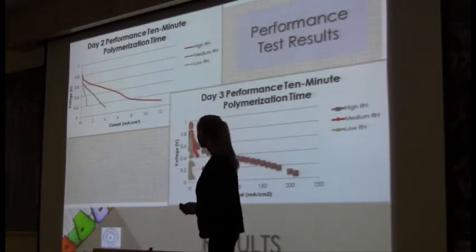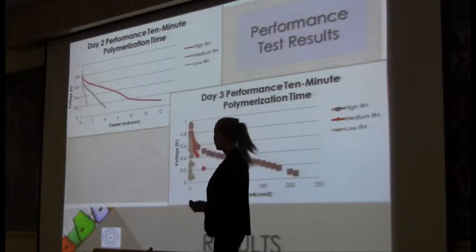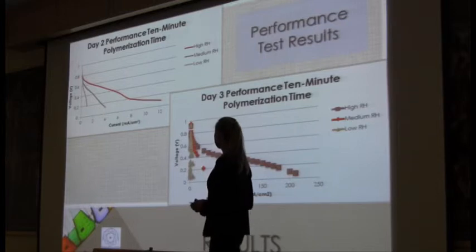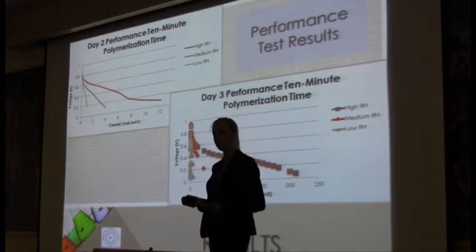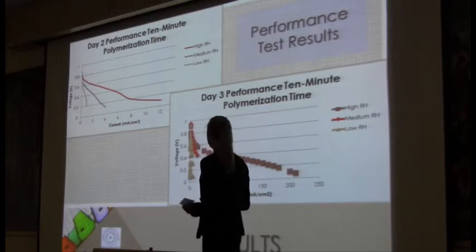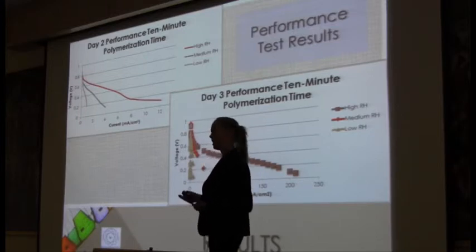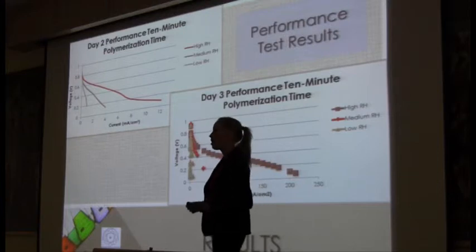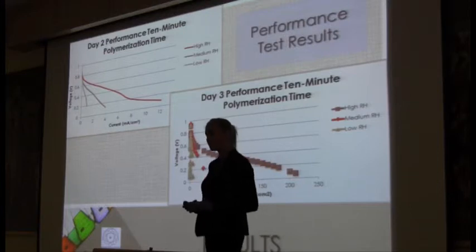The final test we ran was a performance test, and as I said earlier, it was run at 3 different humidities. Day 3 performance 10-minute polymerization time shows after the fuel cell was degraded, and for both day 2 and day 3, we can see that the fuel cell performed best at a high relative humidity. The performance test on the 2-hour polymerization time fuel cell also failed.